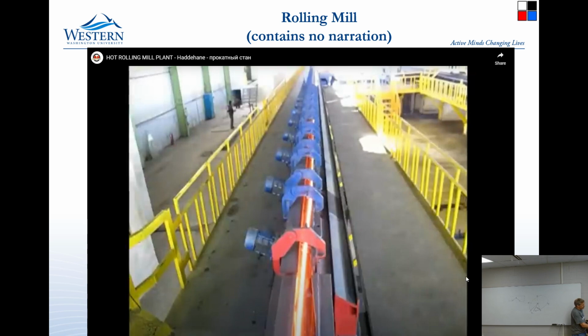So there used to be one of these that unfortunately got taken down. It was this plant in India, and these rolling mills are often a half mile to a mile long. They just keep going. And at the end of this one, it turned the corner and went back. But they had this huge floor area because they needed to slow it down going back. When you start down the set of mills, it's going really slowly. By the end, it can easily be going about 60 miles an hour. And so you need to slow it down to feed it back into the other direction. You don't want to have to start that at 60 miles an hour and end up at 100 or something.